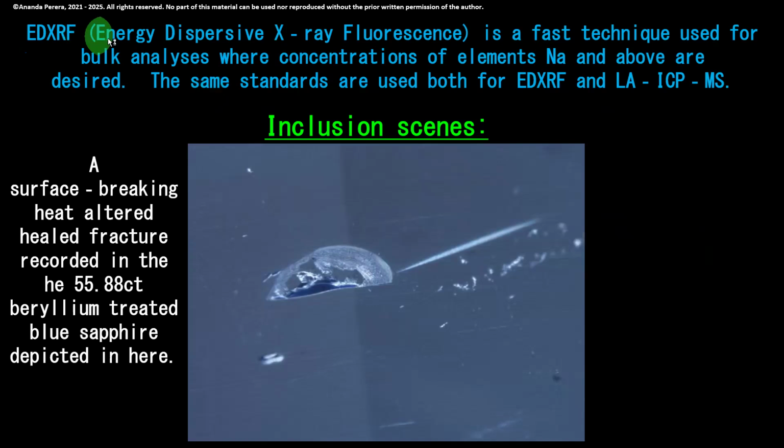EDXRF, energy dispersive X-ray fluorescence, is a fast technique used for bulk analysis where concentrations of elements sodium and above are desired. The same standards are used both for EDXRF and LAICPMS. Now we are moving to inclusion scenes.